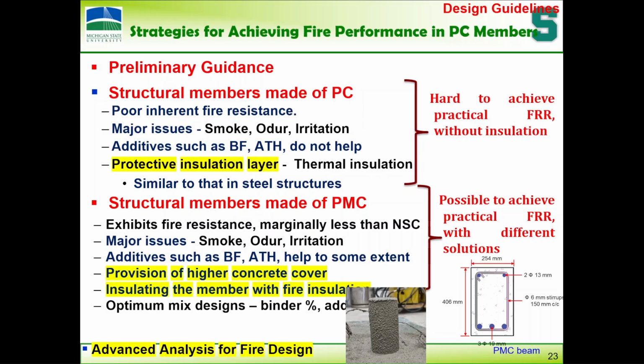I mean, it might change, but currently what we are working on or thinking about is how to make sure these polymer modified concretes can go into the field, if it is used widely, going into ACI guidelines and stuff. Polymer concretes are very hard to get reasonable fire resistance. Typically in buildings you need 1 or 2 hours, mostly 2 hours, so it's very hard. So, what's the approach? Additives won't help too much. It may be flame resistant and stuff, but not from the point of view of structural fire resistance. So, if you want to go, put some kind of a good protective insulation layer. We are working on that at present by coating.